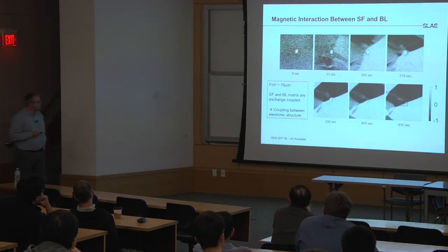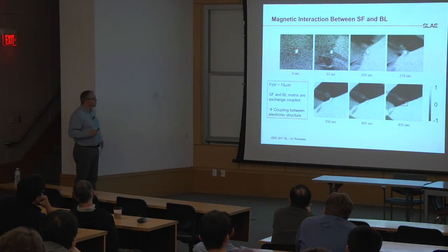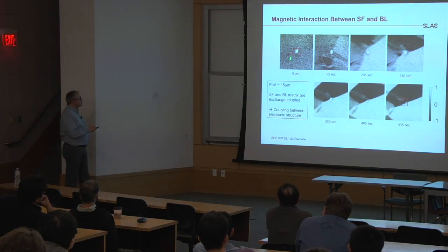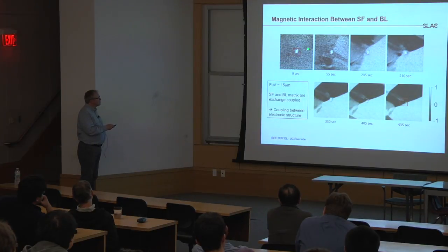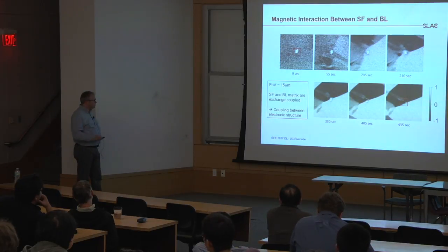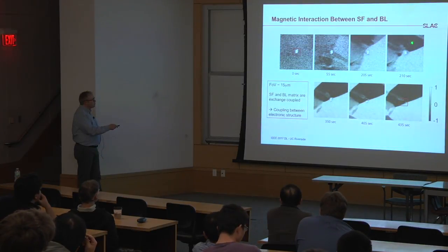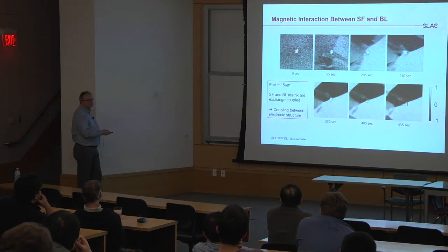And what's actually very nice to see is that these inclusions are not just isolated and separated magnetically from the rest of the material. In this case, we started at a certain temperature above the ordering temperature, and we just started cooling down. And so we have this little inclusion here that is ferromagnetic. And then while we cool it down, the rest around it becomes ferromagnetic. And this little inclusion just turns from white, and all the area around it turns black, because there's a magnetic domain forming that has probably a magnetization pointing in one way, and it just couples to this little inclusion, so it just turns it black as well.